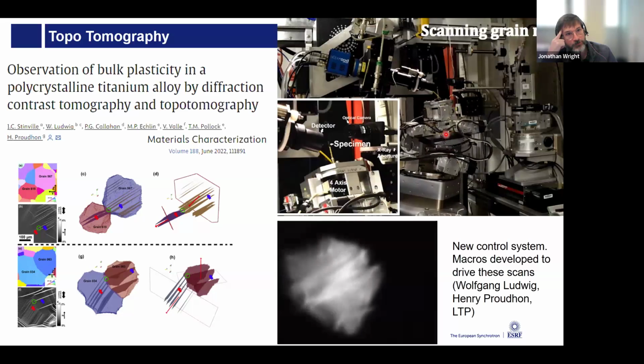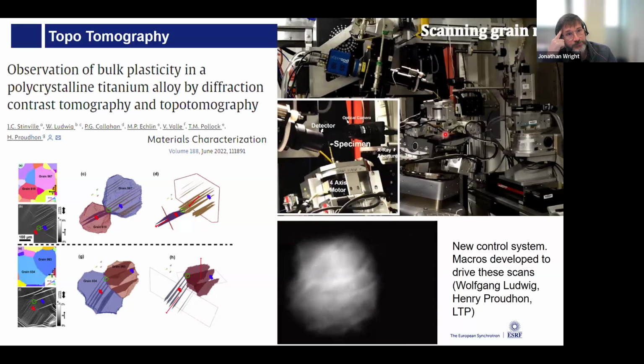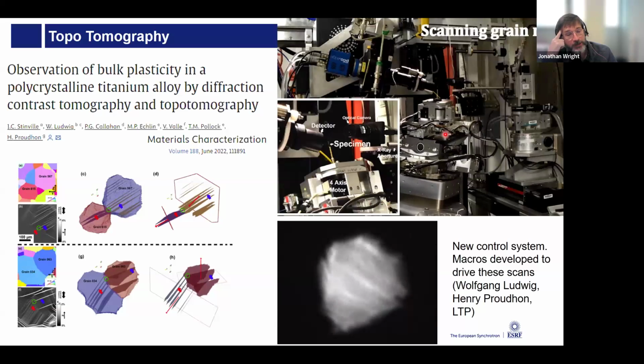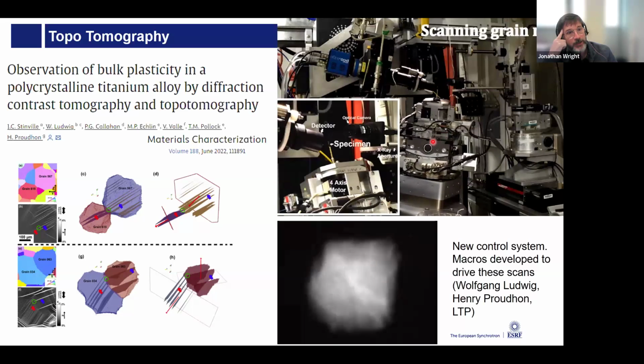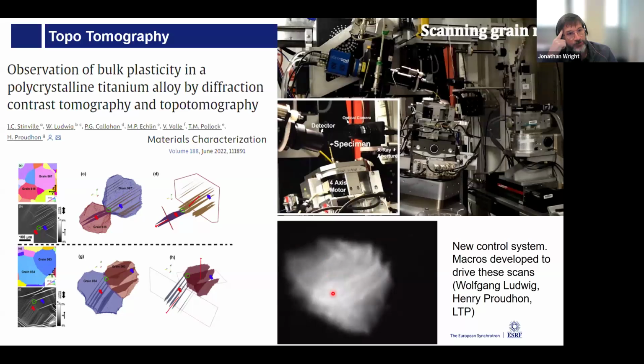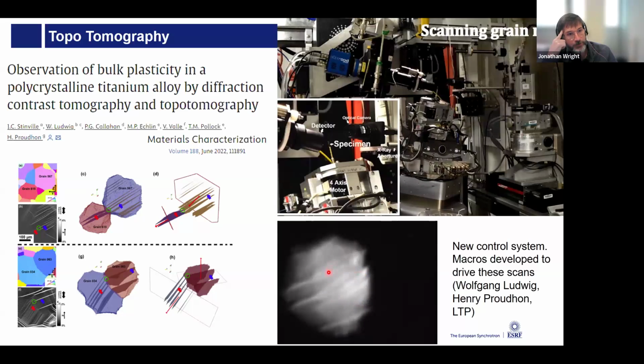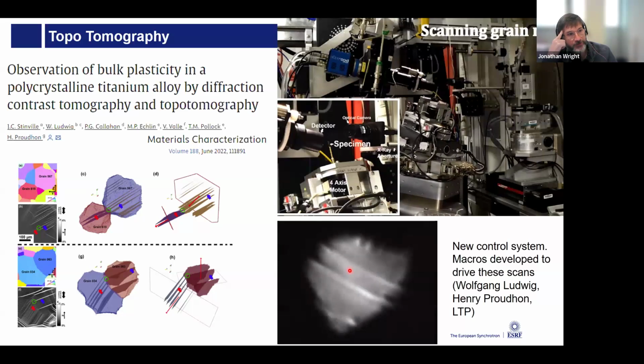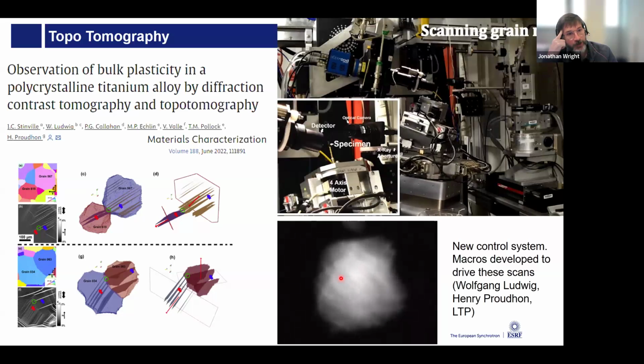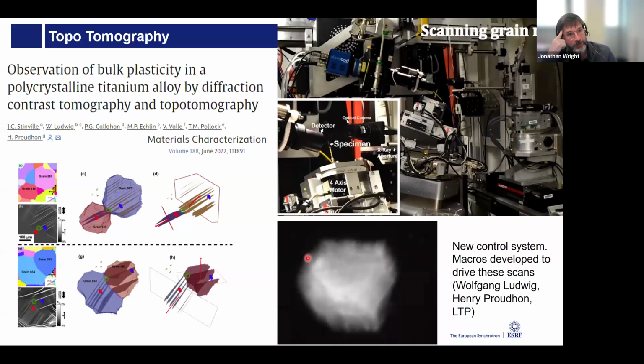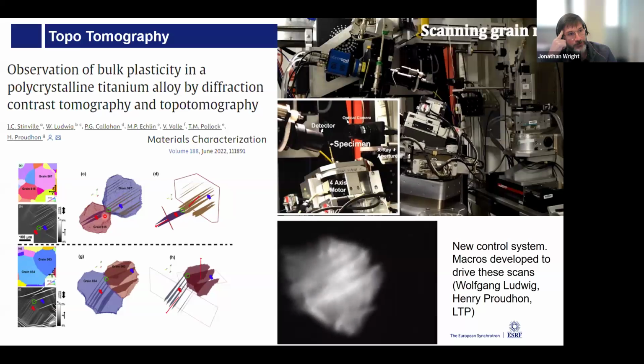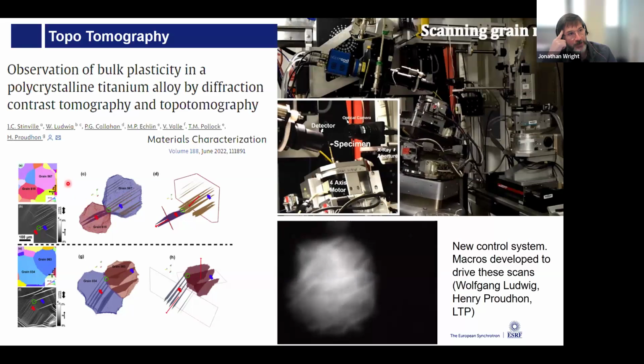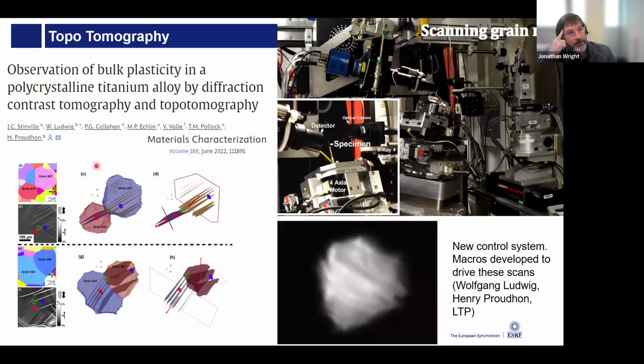Now the diffractometer's gone to find another reflection or another grain. And so the trick here, which is easier said than done, is that you rotate around the scattering vector of one of these crystals and you get this beautiful picture where you see all the slip bands inside. And then you go and find the neighboring crystal that's right next to it, and you do the scan again for the neighboring crystal. And if you succeed to do that, and in this case they did, then you succeed